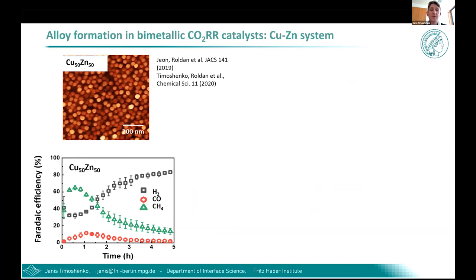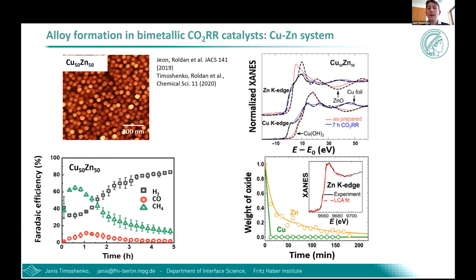So clearly something was going on with the catalyst, it was changing under the reaction conditions, and we used X-ray absorption to understand what's going on. First, we started with XANES analysis, which provided us with important information about the oxidation state of both copper and zinc. In as-prepared samples, both these metals are oxidized, but they are reduced under reaction conditions. What's interesting here is that the reduction rates for copper and zinc are quite different. Copper is reduced almost instantaneously, while for zinc, this process is much slower.